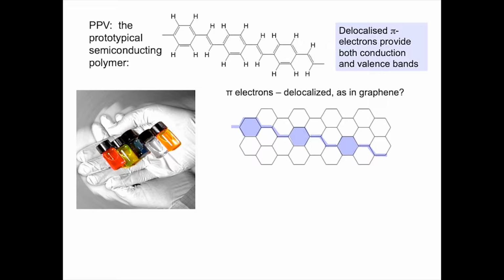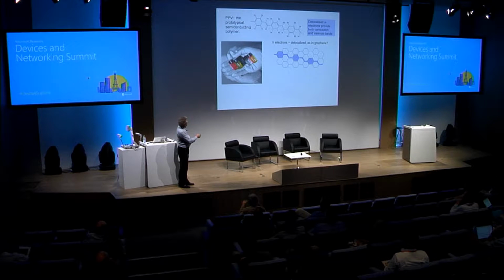I can actually map it onto the graphene network like that. It's as though I've taken this graphene honeycomb network and chopped off the carbons to either side to leave a chain, a sort of nano graphene ribbon, if you like. As we've done that, we've turned on a gap between filled molecular orbitals and empty ones.